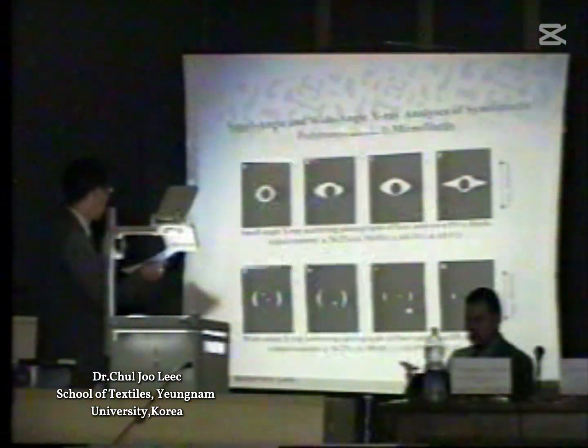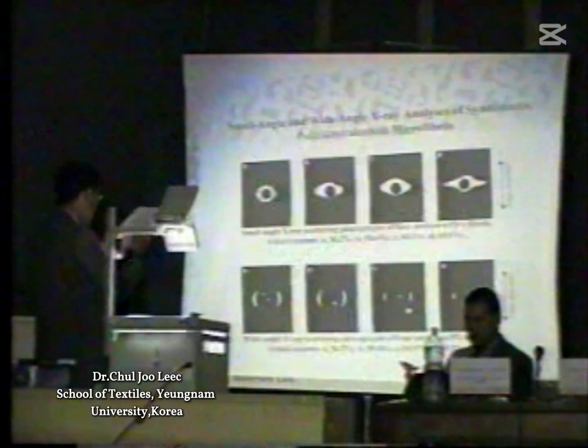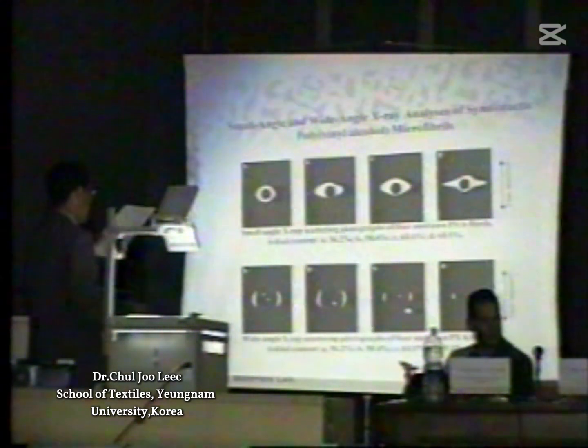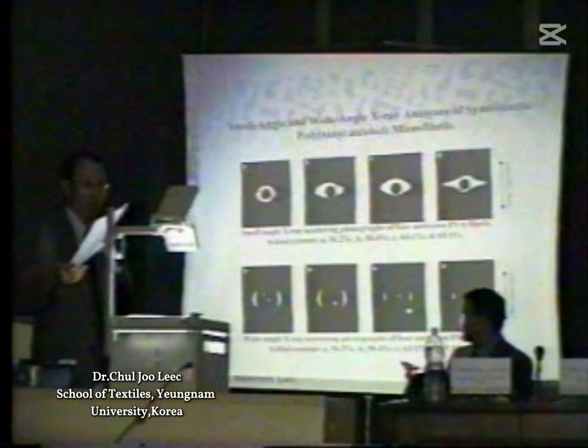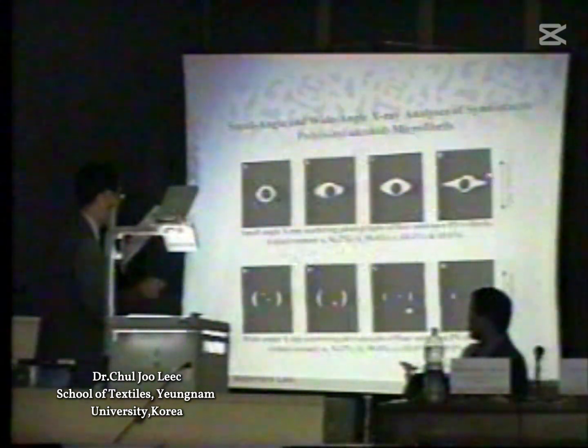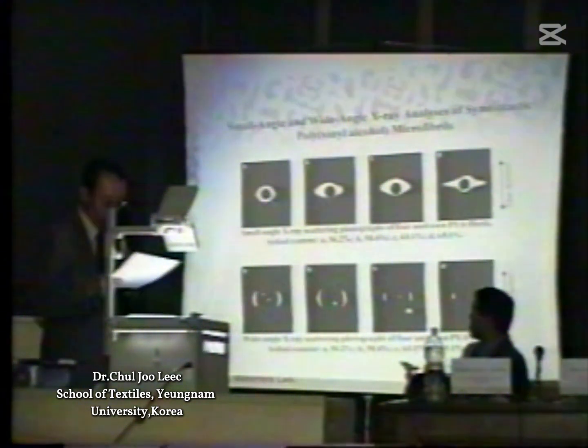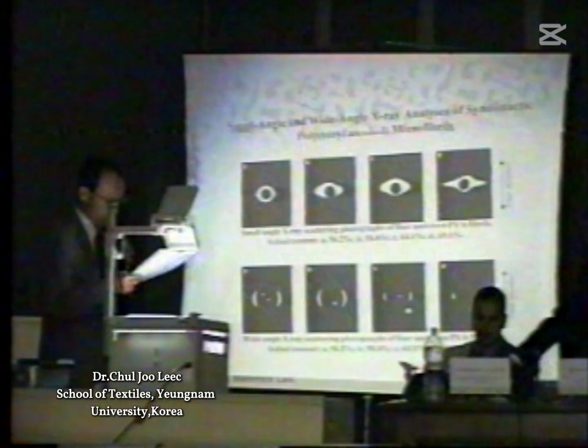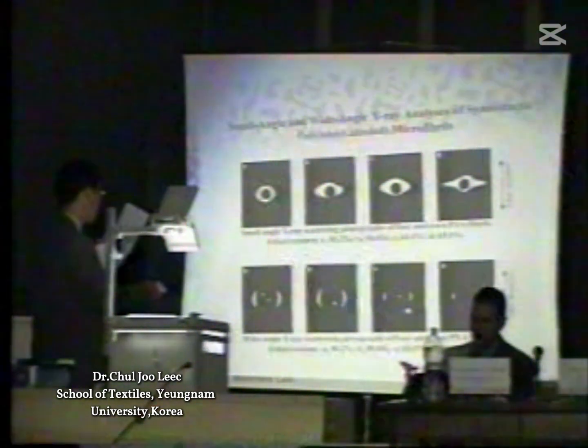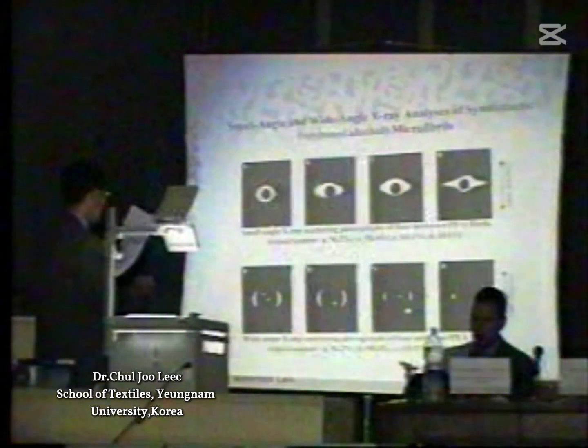The structures of fibrillars having different syndiotactic diad contents were investigated by X-ray scattering patterns. From the small angle X-ray scatterings in the upper figures, we can see the microvoid structure. The evidence is that if a polymer has a microvoid structure, we usually detect diamond-shaped patterns in the small angle X-ray scattering. As the syndiotacticity becomes higher, the microvoids become regular and elongated, as you see from figure A to figure D. The syndiotactic diad content becomes higher from A to D.